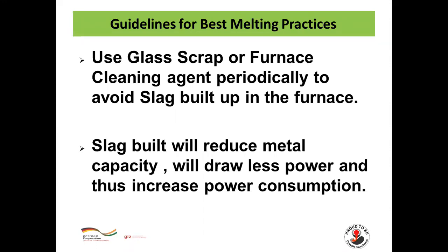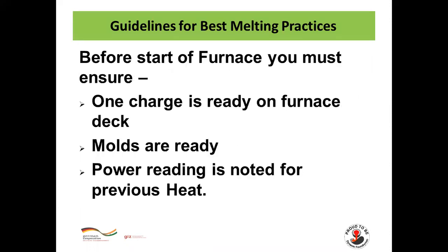Use glass scrap or furnace cleaning agent periodically to avoid slag buildup in the furnace. Slag buildup will reduce metal capacity and will draw less power and thus increase power consumption. So it is very important to keep the furnace clean and slag free.